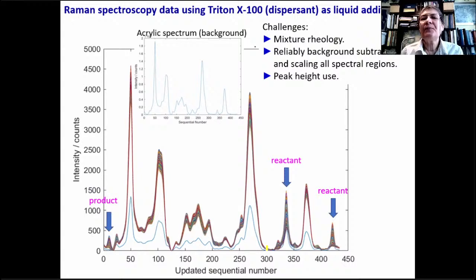So then we tried various additives, and we found Triton X100 as a dispersant or a non-ionic surfactant to form a viscous paste in which we don't know if the reactants are dissolved or suspended, but the rheology can be uniform. It is not always uniform, but it can be uniform for these measurements to happen.